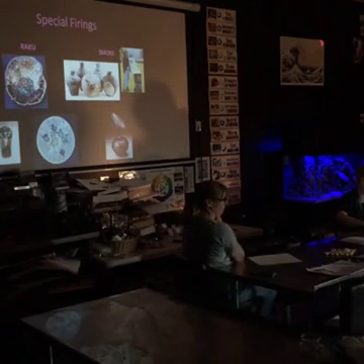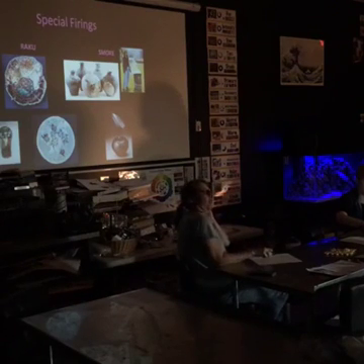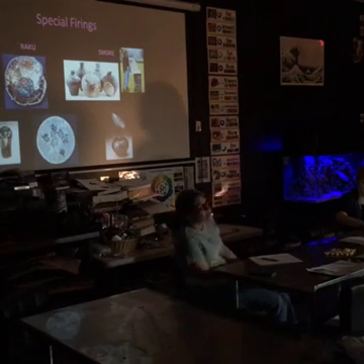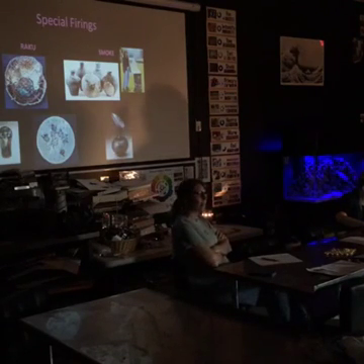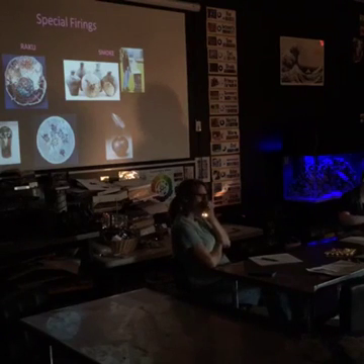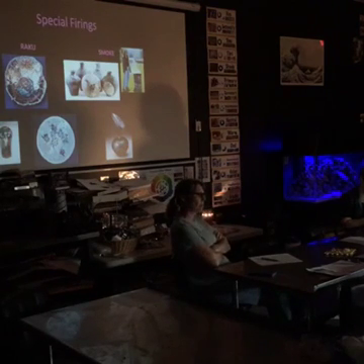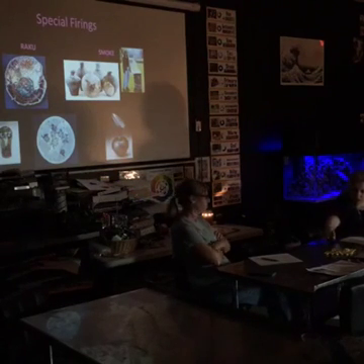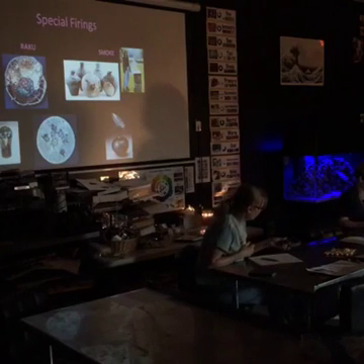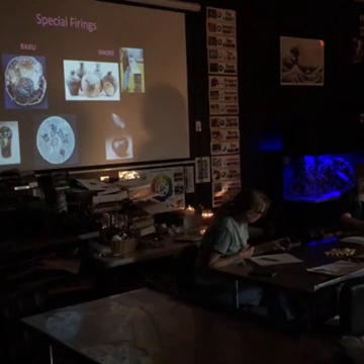So the craziest part of this firing is you do it with a group, and you stick poles in the top of your kiln hood, and then you have two people lift it off, and then really quick, you have people ready with tongs. You grab the hot pots, and then you have to throw them in a trash can full of combustibles, like newspaper and sawdust, close the lid, and the hot pots burn the combustibles, so it sucks all the oxygen out of the air. The lack of oxygen is what makes it get metallic and crazy. Then you gotta grab those, dunk them in cold water to freeze it.